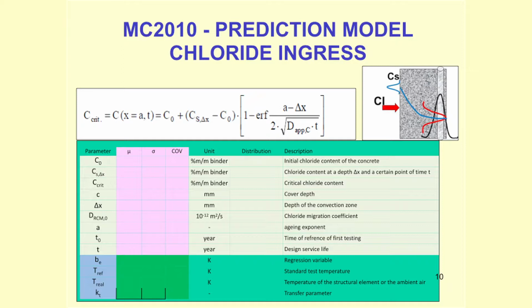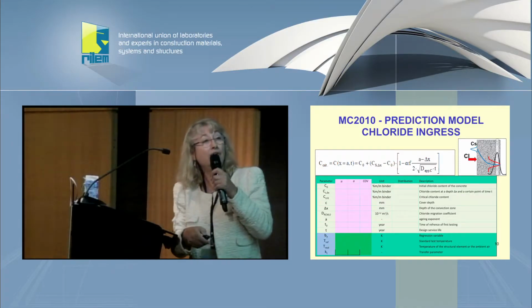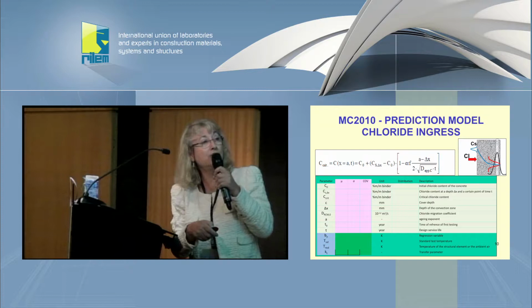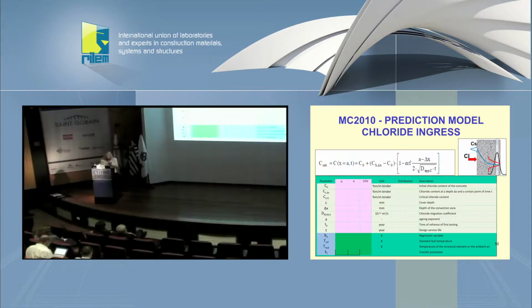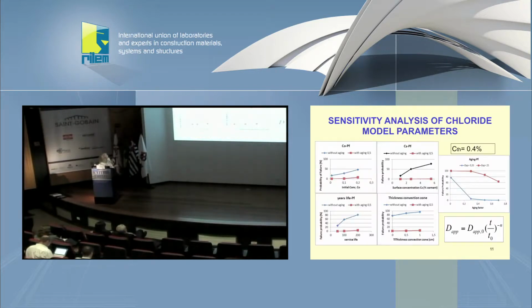Here there are, and I put them in another color, the factors depending on the effect of temperature that I will not talk about, but again, this is conceptual. Really, when you have higher temperatures, if the concrete is not saturated, the Arrhenius law cannot be used. It can only be used if you have a completely saturated concrete. Okay, just introduced in an Excel file for the probabilistic treatment or in another program.